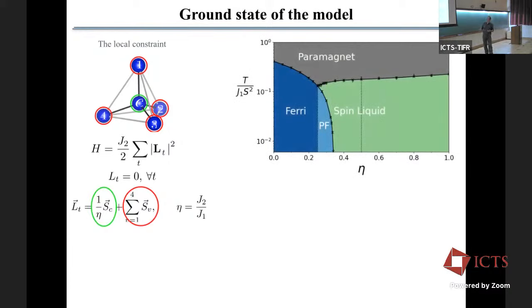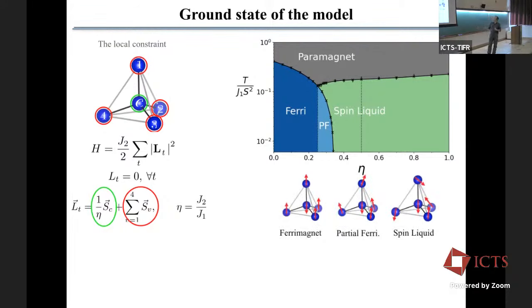Now, as you increase eta, so as you increase J2, this central spin will have less and less influence. At some point, you will be able to have some tilted angles. So this is perfect ferrimagnetism. Here in this region, you will have partial ferrimagnetism. And at some point, it will be possible for all of these 5 spins, even with the term eta, to cancel each other. And so this term here will be equal to 0. And this will give rise to a disordered classical ground state, which is this classical spin liquid, the green region that you have here.